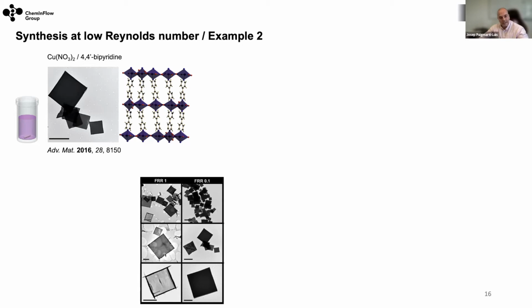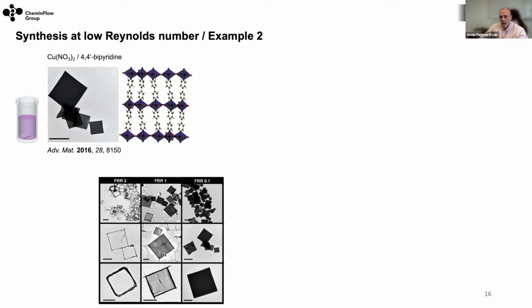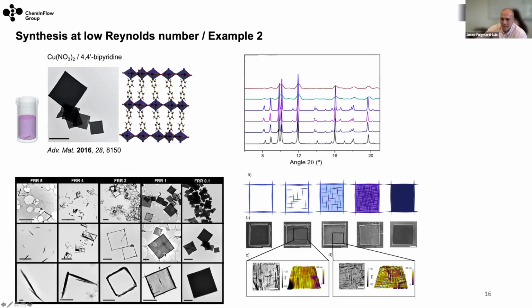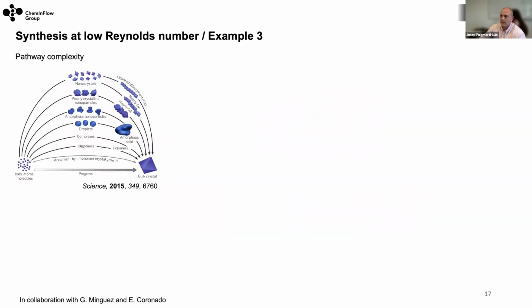But as soon as we start to increase the flow rate ratio, what we realize is that now we are achieving a series of unprecedented structures that we cannot obtain in bulk synthesis even when we add surfactants. So it's not possible to achieve these structures. We can only achieve them when we do the microfluidic synthesis. And this is what we observe also: the diffraction pattern of all these structures is the same. So what we have here is a clear case where we are freezing the crystallization process towards this most stable thermodynamic form in this coordination polymer.